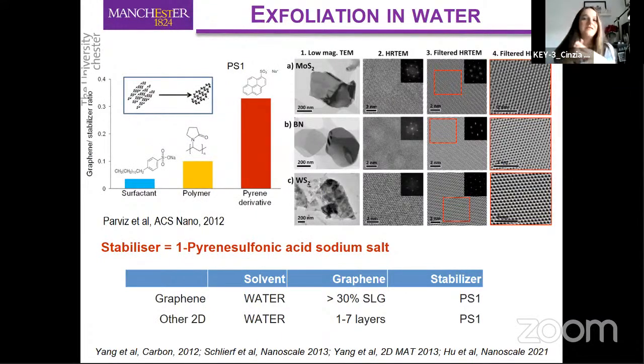So first of all, we started with the exfoliation of graphite and layered materials in water. It's very well known that it's possible to exfoliate those materials by using stabilizing agents, exfoliating agents, typically surfactants or polymers. However, in our case, we decided to use small aromatic molecules as an exfoliating agent. Indeed, if you look, for example, at this molecule here, you can see that this is basically a molecule that will work as a surfactant. We have a hydrophobic part, which is given by the pyrene core, which will interact with the graphene through pi-pi interactions. And then we have the charged group here, which will enable electrostatic stabilization in the water.